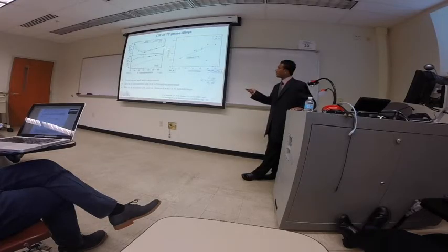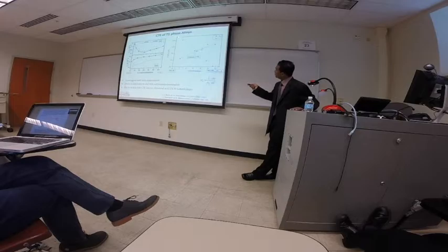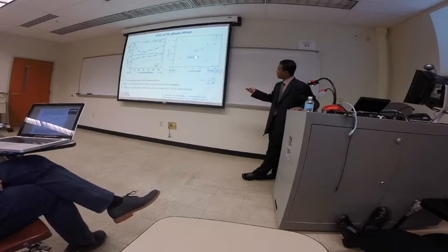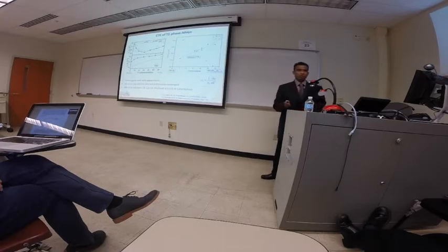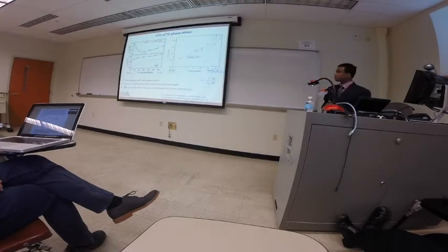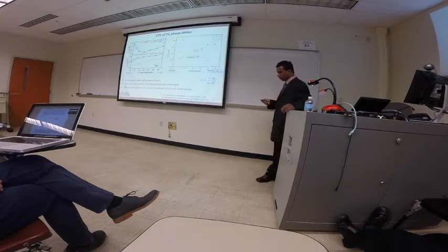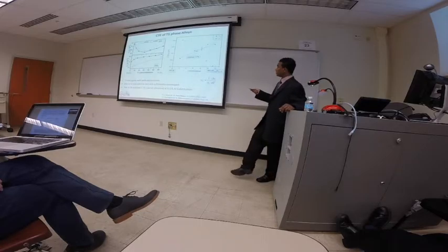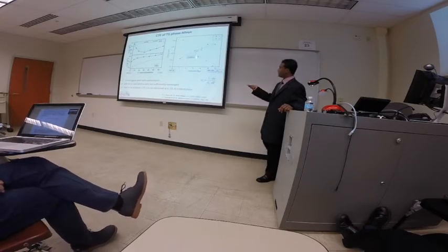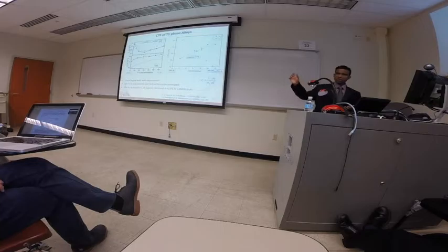You can't make zero anisotropy with the vanadium alloy, except for the aluminium case, where the thermal expansion of A and thermal expansion of C intersect in the middle. So at this percentage, you get an alloy with zero thermal expansion anisotropy. So we predict that at this composition, you'll get a much better alloy with zero anisotropy.